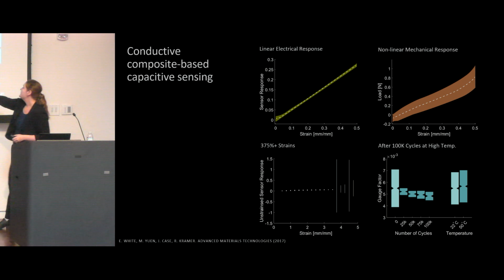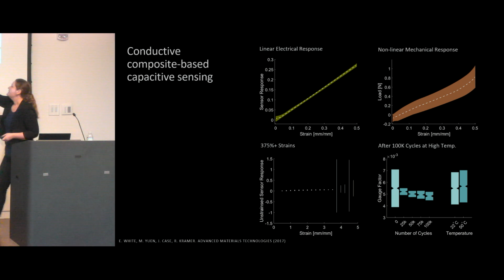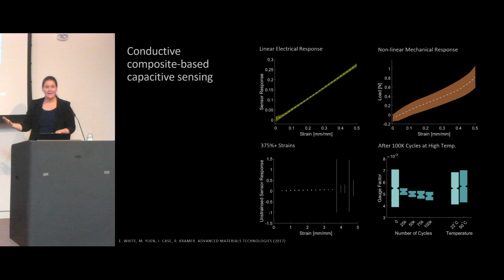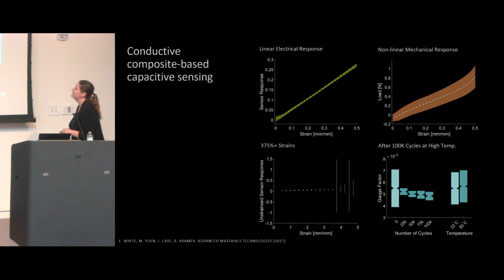And we also looked at drift over hundreds of thousands of cycles. So we cycled our sensors to 100% strain for 100,000 cycles, and we saw very little drift in the gauge factor, which is a measure of the sensitivity of the sensor. And working alongside NASA, they also encouraged us to look at temperature variations and environmental variations overall. So we did look at some slight temperature sweeps between close to room temperature and a little bit warmer, and again saw a lot of stability in the gauge factor, or the sensitivity of the sensors.